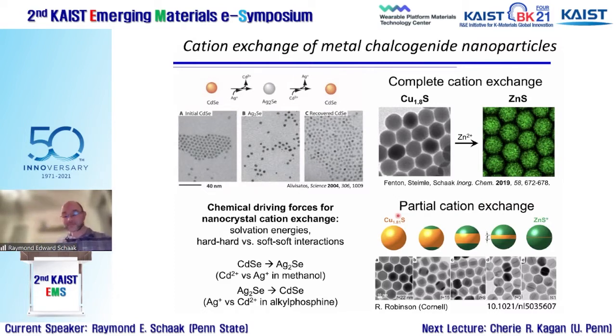So this is showing work that was really inspirational to us. This is from Richard Robinson's group at Cornell, taking the same kinds of copper sulfide particles that we work with, same zinc exchange reaction, but showing that carried out not to completion, you actually get some really interesting features and effects. In this case, the zinc exchanges at the poles. If you think about this as the globe, the exchange is happening at the north and south pole at the same time. And the result is you systematically introduce zinc sulfide into this copper sulfide sphere. So you're breaking the symmetry and making these sandwich-like particles, where the amount of zinc sulfide relative to copper sulfide tracks with how far you go into the reaction.